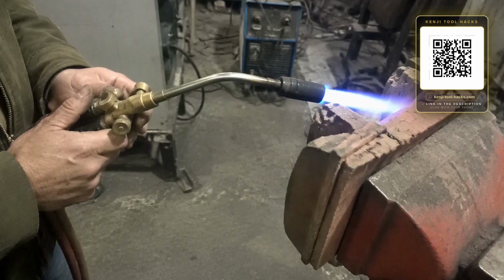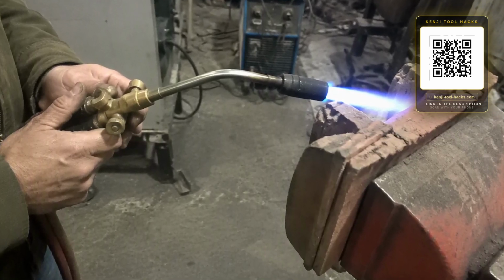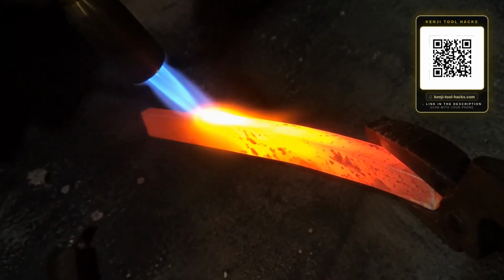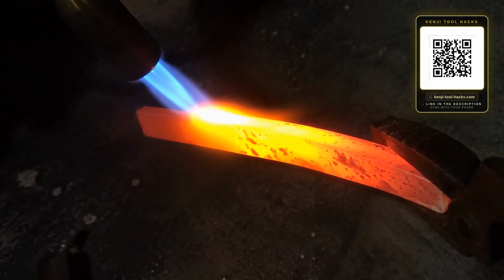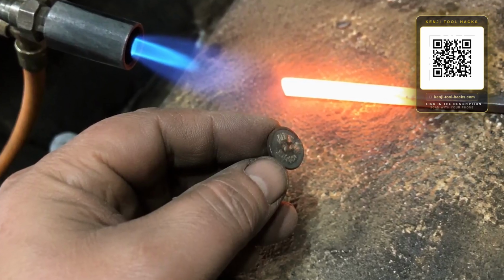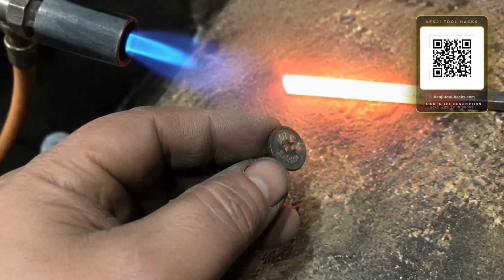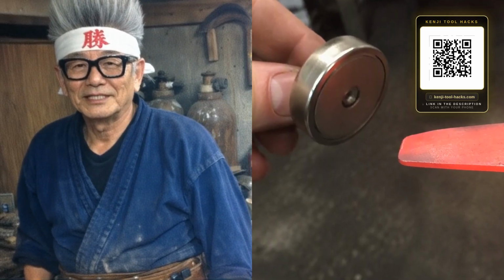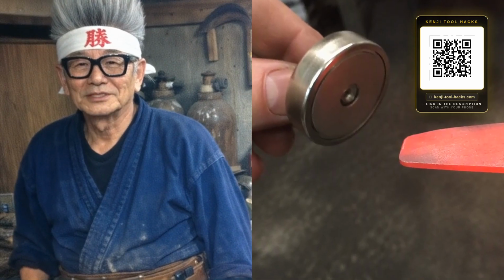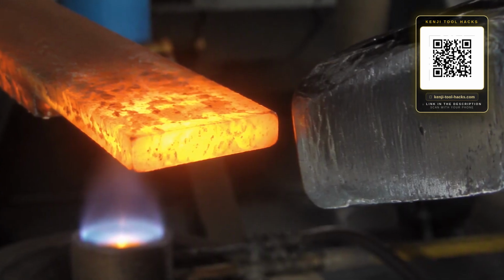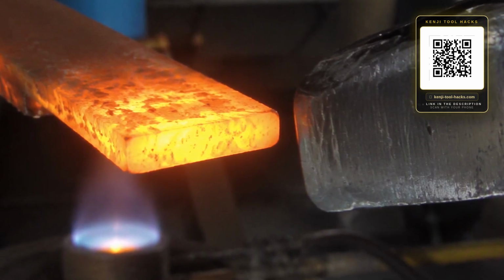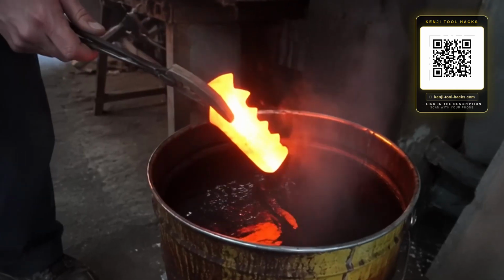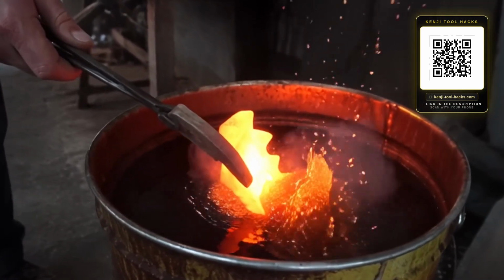Now the heat. Take your propane or MAPP torch and heat the bare edge of the jaw evenly until it glows a bright cherry to orange, somewhere around 1400 to 1500 degrees Fahrenheit for common carbon steel. The way the old smiths judged it without a thermometer is a trick you can use right now. You hold a magnet near the steel as it heats, and the exact moment the steel stops sticking to the magnet, it has reached the critical temperature it needs to harden.